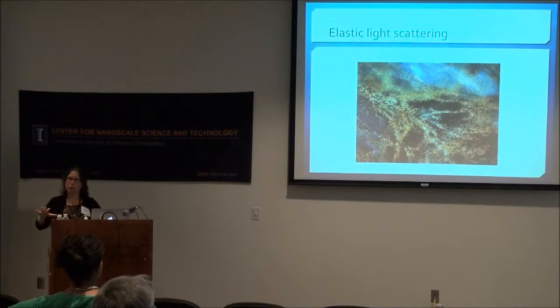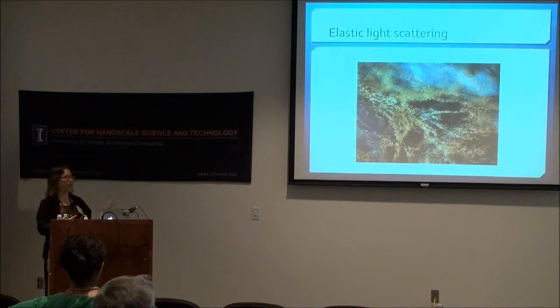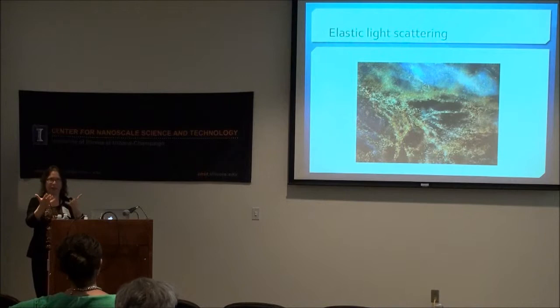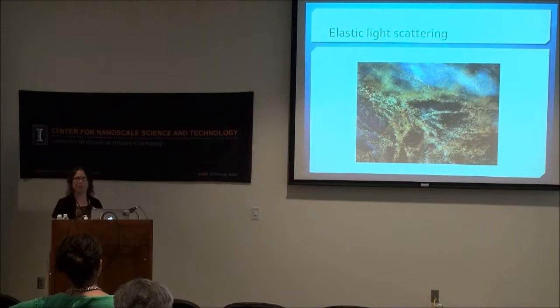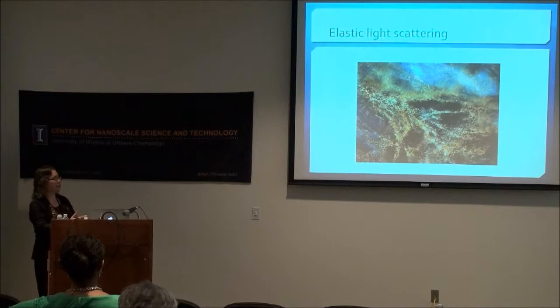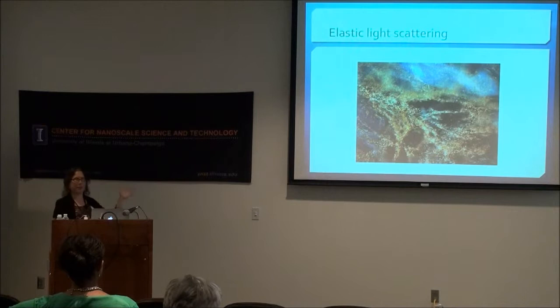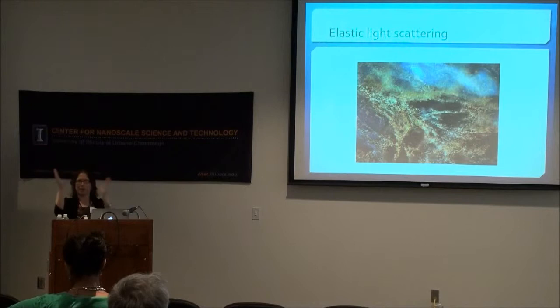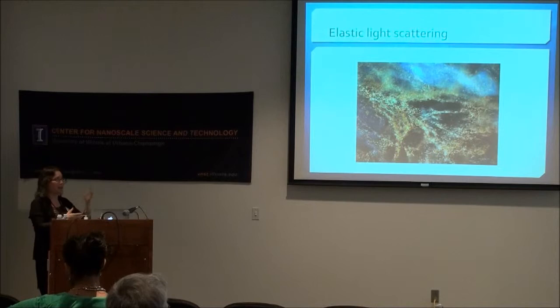In addition to strong absorption, these particles scatter light very well — elastic light scattering. Shown here is a dark-field optical micrograph of rod particles dispersed in a polymer gel. White light comes in and we observe the elastically scattered light from the sides; the field of view is about three millimeters, so all those little stars you see are our particles. You can even extract the orientation of the rods from this, because the scattered light color reflects which absorption band is aligned toward you — scattering blue, red, or different colors depending on angle. Single-particle optical experiments are possible in this kind of microscope.